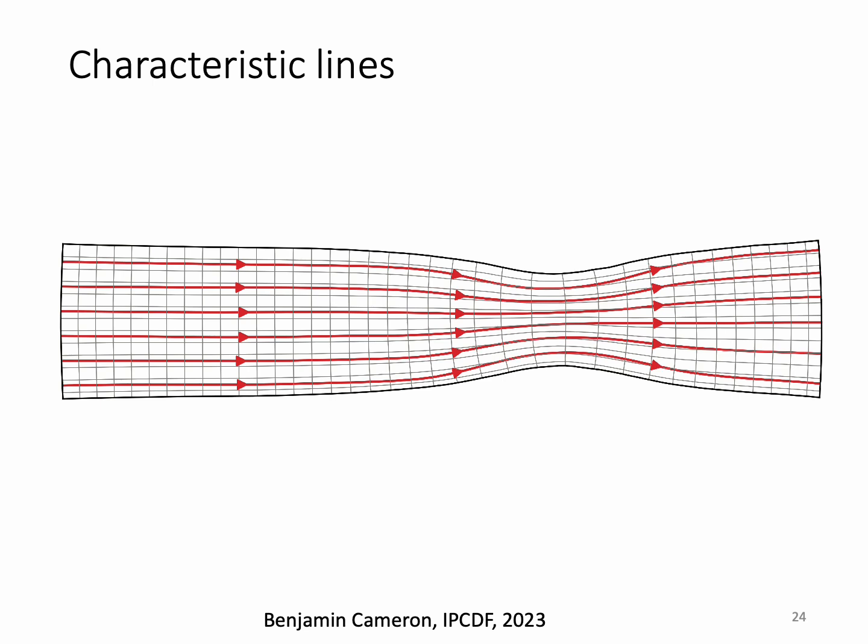So we specify the traction on the left-hand side. Then we follow through, calculate the stress on the left of the neck, follow the lines, calculate the stress in the center of the neck, out on the right-hand side. And you actually calculate the traction on the right-hand side as part of the solution. So you only actually have to specify part of the traction boundary conditions.